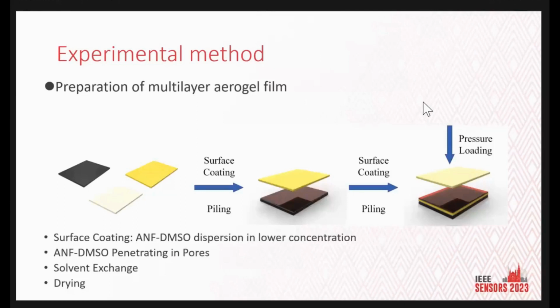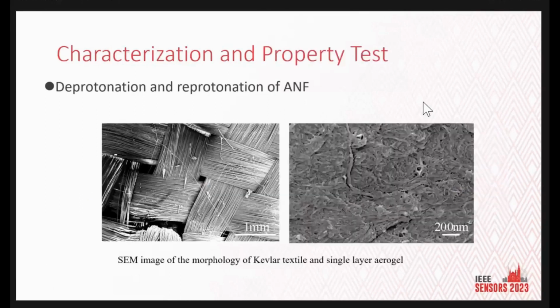And after the last step, we coat a thin layer of aramid dispersion on the surface of the aerogel film, and we pile them together and load a pressure on top of it to help the dispersion penetrate into the meso and micropores. Then we repeat the process for solvent exchange and drying. So next, let's introduce our